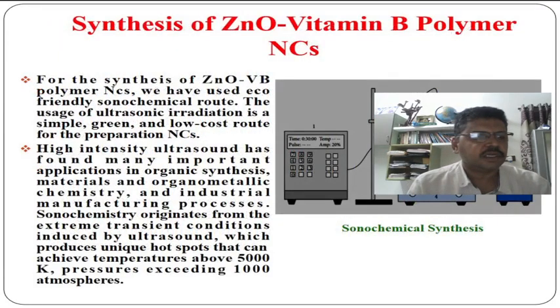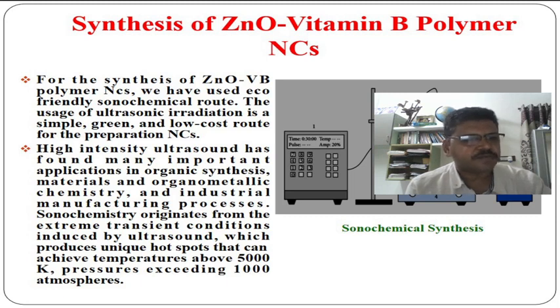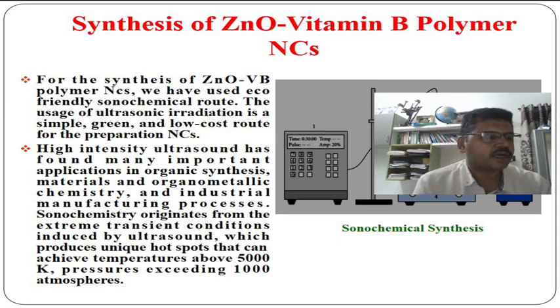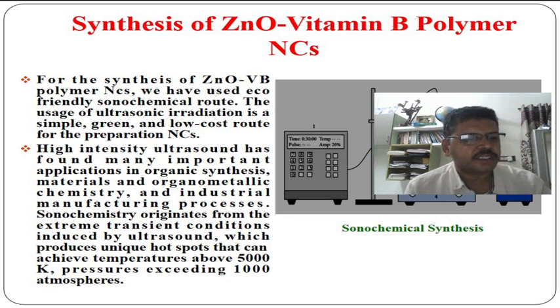So next, after knowing this concept, the synthesis of ZnO vitamin B polymer nanocomposites. Vitamin B1 was used for surface modification of ZnO nanoparticles. According to this, for the synthesis of nanocomposites, it was poured into deionized water by heating and continuous stirring to obtain a clear solution, and subsequently was dispersed via ultrasonication for 50 minutes.